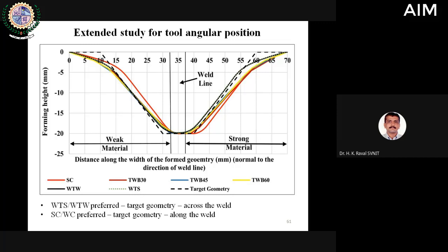These results are very clearly indicating that if you take the plot along the starting point, that is SC, the black dotted line is the target geometry, and SC is a geometry which is taken at the starting point in the strong center. It is deviating much compared to the others. And you see, eventually as the angle of starting point increases, 30 degree, 45 degree, 60 degree, and ultimately WTW, the deviation is reduced, and it is in agreement with the target geometry.